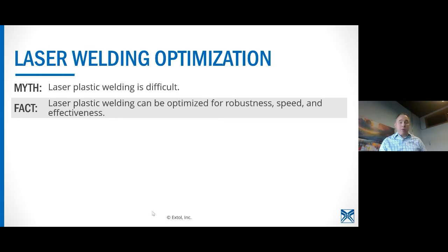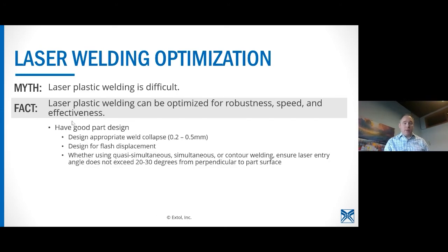And then to continue that, 2 more points on laser plastic welding being difficult. Have good part design. We can help with this. At Xtol, we've got a process development center that can help with your weld joint design, and just 3 sort of high level items within this category. Making sure that there is an appropriate weld collapse. 0.2 to 0.5 millimeters we see most common, but a lot of times people think, well, I'm not melting as much, so I don't need that weld collapse. And in some cases that's true, but in other cases we most often see that it is required.